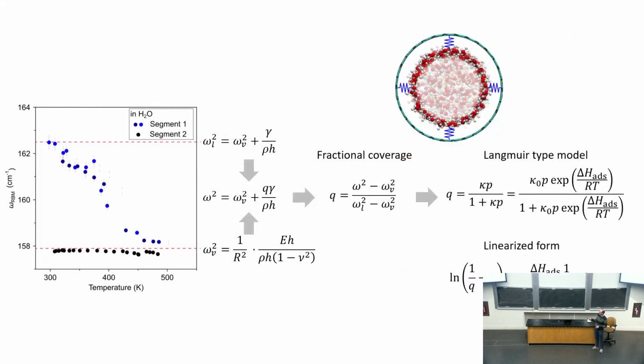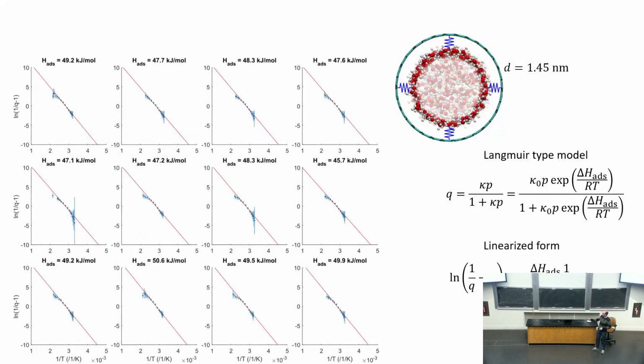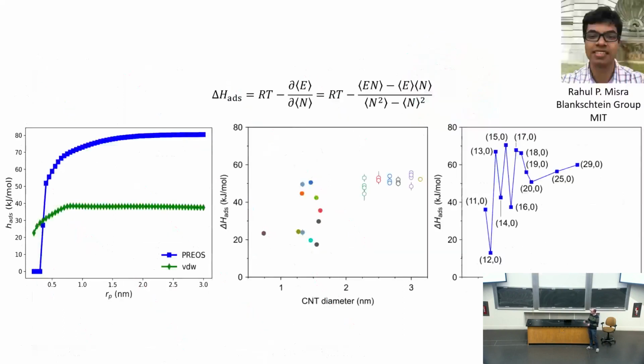So motivated by this, we look at these measurements that we did. We can mathematically convert this change in frequency to a change in coverage. And from the coverage, we can take an adsorption model to describe this sort of phase transition that's going on here between a vapor phase and a liquid phase. And we can do that for different scans. We repeat these over and over. There are hundreds of scans on dozens of tubes that we did. We can do this to extract these enthalpies that describe phase change. And what we find, curiously, is that they actually vary quite a bit over small diameter ranges here.